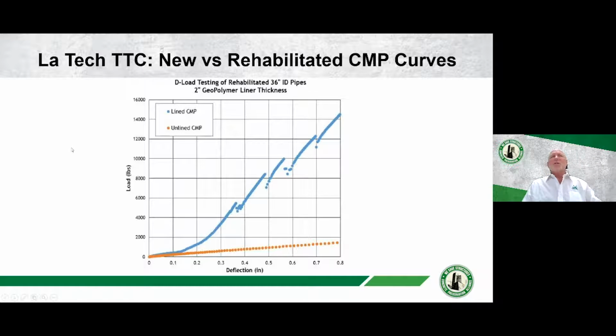There was a lot of different configurations, but for today, what we're going to look at is we're interested in corrugated metal pipe. So this is a load deflection curve for a 36-inch diameter pipe with 2 inches of geopolymer liner on it. As you can see, the orange line here, this was a corrugated metal pipe that was tested in a D-load test. As you can see, the D-load test is not designed for testing corrugated metal pipe. It basically just crushed. Because with the corrugated metal pipe, we're relying so much on the soil load distributions for making that pipe effective. But once that culvert was lined, you can see the significant increase in strength in the load deflection curve with the liner in place.